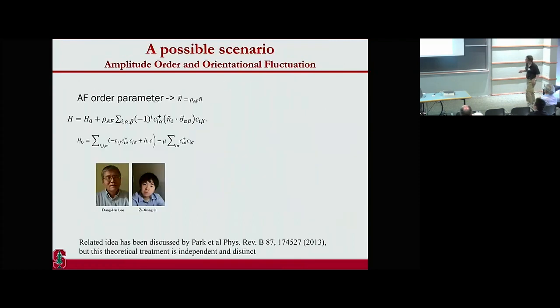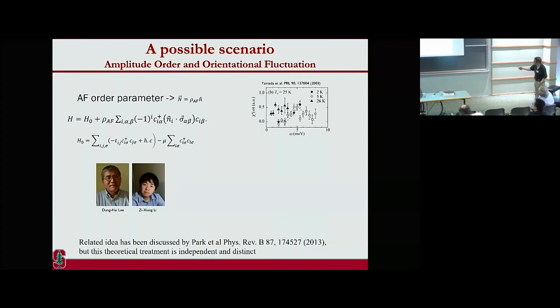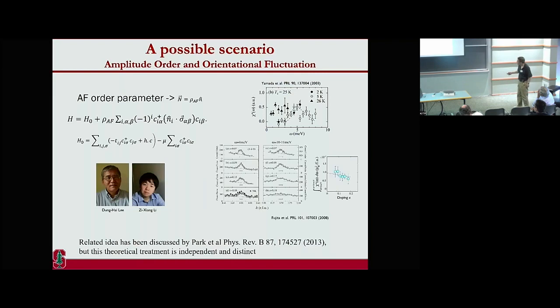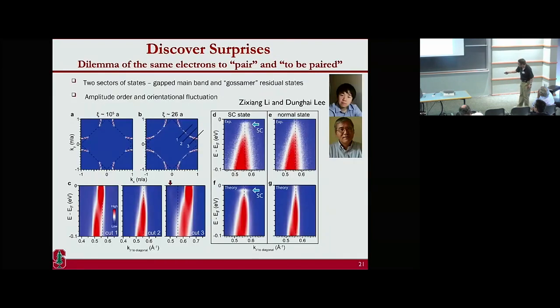The work Dung-Hai Lee and his collaborator did was basically taking into account the fact that the integrated moment of spin in this system is a constant as a function of doping. So throughout the doping process, the amplitude of the antiferromagnetism doesn't change, but the orientation has a fluctuation. I'm not going to go into it. With that, they can actually reproduce the result, especially the ghost-like Fermi surface. This paper will come out soon, so those details are all in the literature.